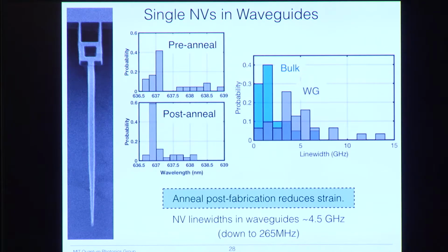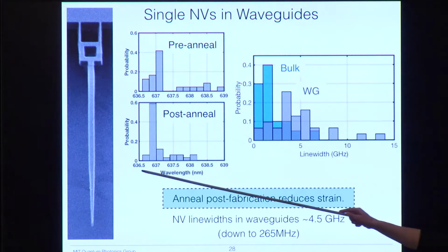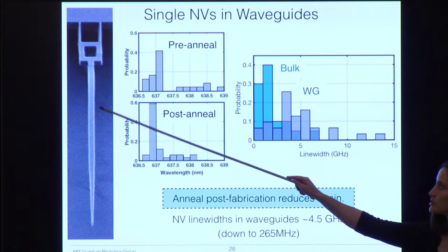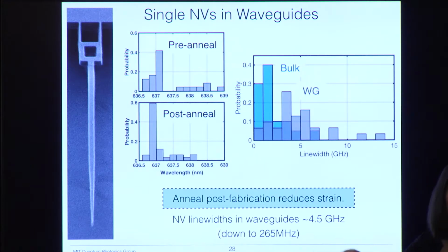So we want to investigate this a little bit and see how good we can get these nanostructures, and see if there's any hope of getting a high quality NV center in a cavity with high Q and low mode volume. So first, let's just look at NVs in single mode waveguides. That's a structure kind of like this. You'll see no holes, but it's still a single mode waveguide with a cross section of about 250 by 250 nanometers.